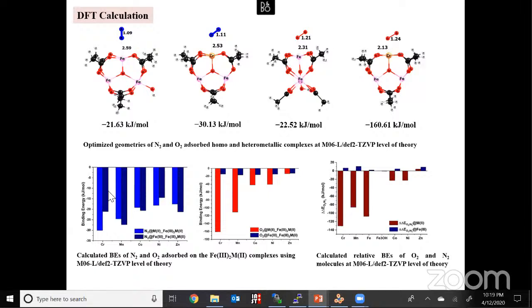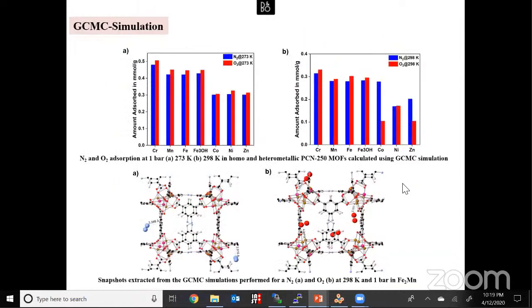And the corresponding calculated binding energy graph also shows that compared with nitrogen, oxygen is binding effectively over the model cluster, and the relative binding energy graph also shows that oxygen is selectively binding over the cluster than the nitrogen molecule. And in order to validate our quantum mechanical result, we did GCMC simulation studies for all these 7 clusters.